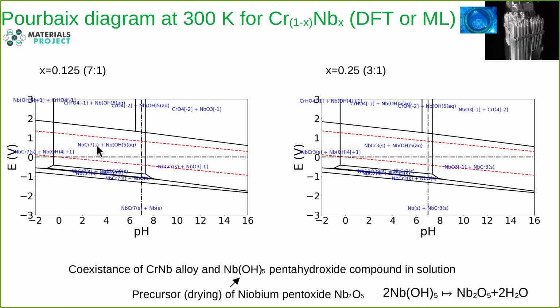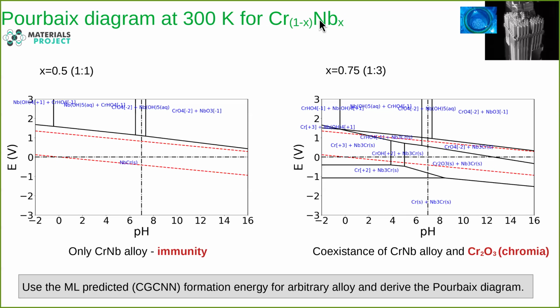That will be the alloy, the corresponding alloy that you actually use. And also there will be some pentahydroxide compound in a solid solution. If you increase the niobium content, you will get this situation, which is the same. Again, the alloy will be stable, plus there will be some solution with this particular pentahydroxide. If you further increase the niobium content, to go to 50-50, then you will see that the chromium niobium alloy will be stable at that particular setup where you have no electrode potential and pH at 7. So that we call the immunity region, where the coating will stay as it is.